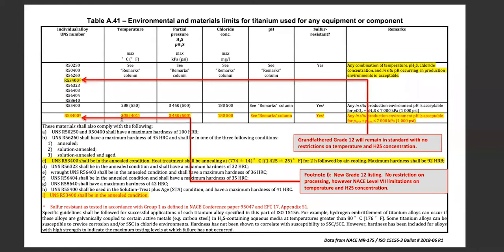And as an alternative, what we did was add a footnote I. And you can see that for the footnote I, any new grades that get added or modified, you have to have limitations on temperature, partial pressure, chloride concentration, pH levels. And that's all based on the corrosion testing that was performed in order to get this added to the standard. So although we do have the restrictions, there are no restrictions on processing. We do have the NACE level 7 limitations on temperature and H2S concentration. But if you look at the footnote I, UNS R53400 shall be in the annealed condition. So the restrictions on how to anneal the material and also the restrictions on hardness have been removed.